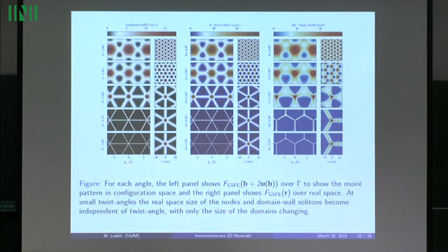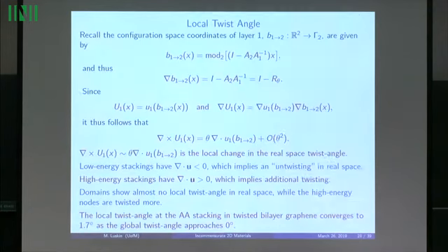But if I map it into real space, in fact the width will eventually be constant. So as we go to very small angles, the Moire cells get huge, but the width of the interface is constant. And we have similar things for the 0 degree molybdenum disulfide and 180 degree molybdenum disulfide.